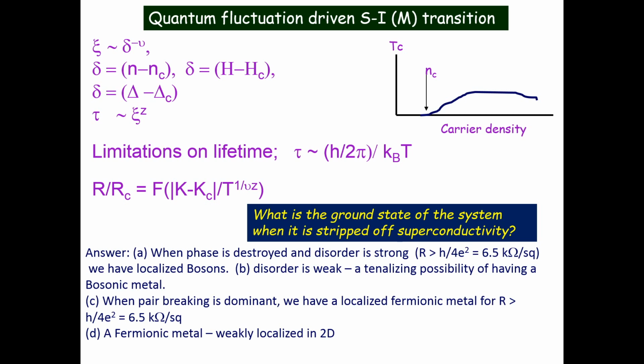But it is still not established that there is indeed a bosonic metal in these systems. And then when pair breaking is dominant, you will have fermions, and if the resistance is more than this, then you have a localized fermionic system. And if the resistance is less than this, then you can say a weakly localized two-dimensional conductor. So there are many possibilities depending on whether you are playing with the phase or with the amplitude.